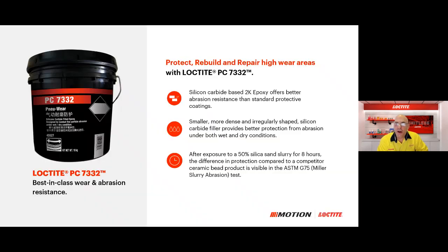And you can see in that video, if you're paying attention, you'll see the competitor product on the right-hand side had literally worn right down to the clamp that's holding the sample in place, and the Loctite sample on the left-hand side looked barely worn at all. So as we like to point out, typical example would be 2 to 3 times the life of a lot of the competitor products out there. And in this case, it's definitely best in class. It's the highest wear resistance of any product in this type of product range out there in the market.